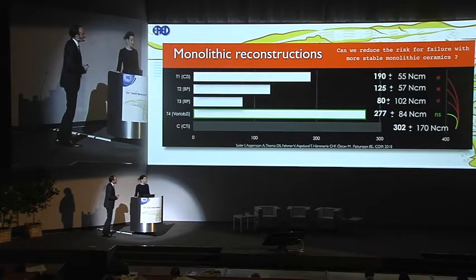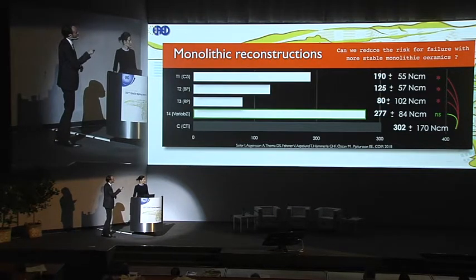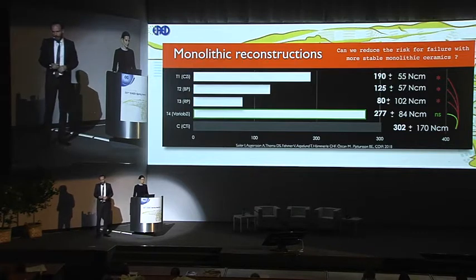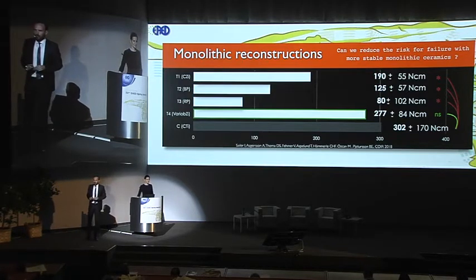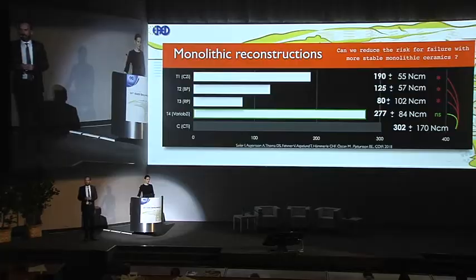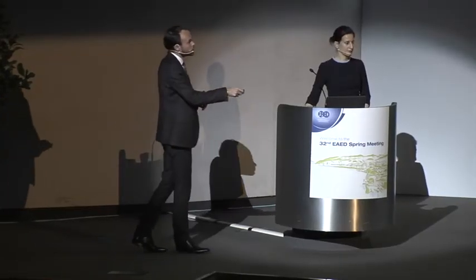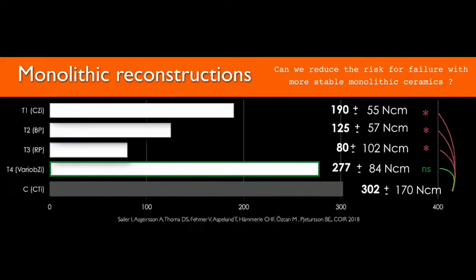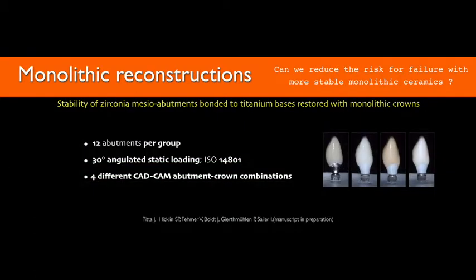And this also counts up in values. You see here the zirconia abutments on the top in white, and you see then the two groups on the bottom, basically the titanium resin base with the titanium abutment. No significance in the difference between those two groups. So very promising. But those abutments are basically not what our patients are interested in.